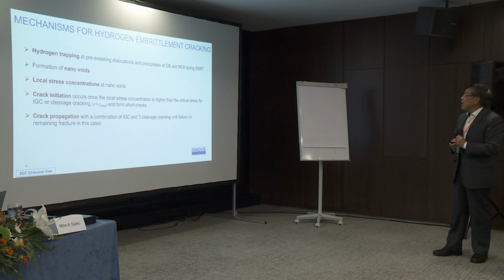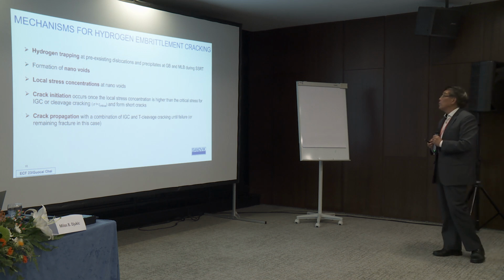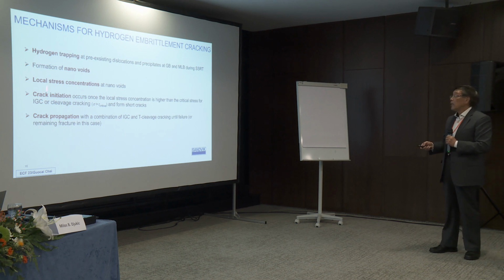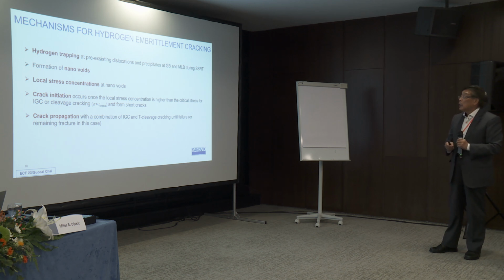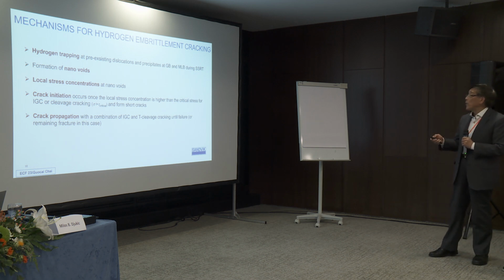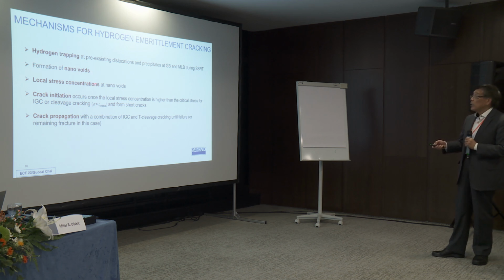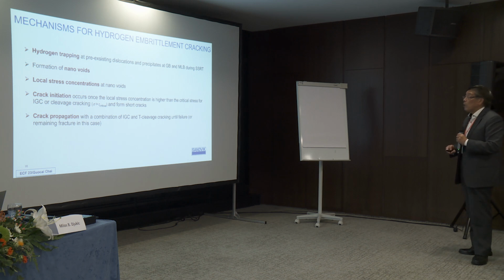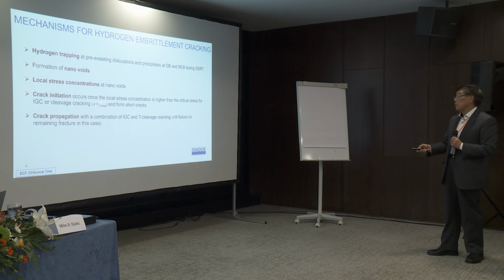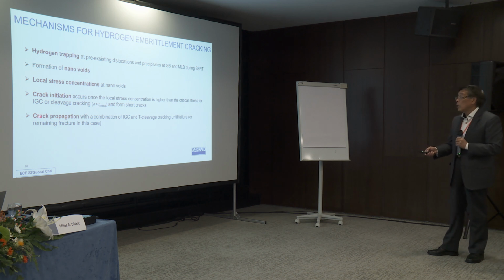So here is the mechanism for hydrogen embrittlement cracking in these materials. First is hydrogen trapping, either at dislocations, slip bands, or the interaction of dislocations, or at intermetallic phases. Then it forms a void. Due to local stress concentration at a grain boundary or void, it will cause crack initiation, especially when the stress concentration is high enough. This is the critical stress we need to study. Then it causes crack propagation.